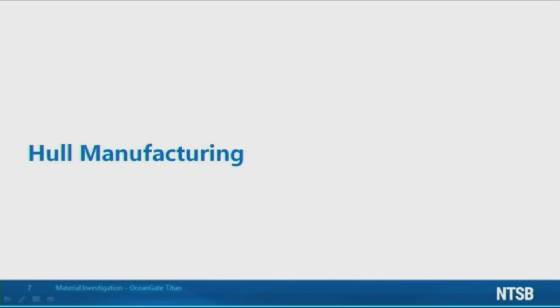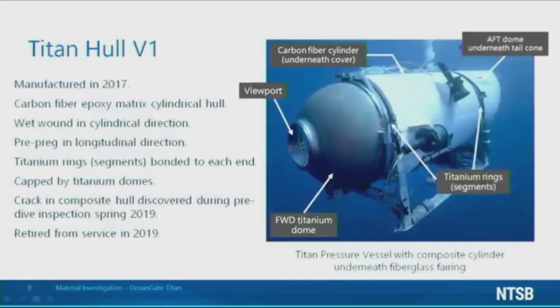I'll now discuss the manufacturing of Titan's composite hull. The Titan V1 cylindrical composite hull was manufactured in 2017 and was at the core of the Titan pressure vessel. The hull was manufactured using a combination of wet wound fiber for the circumferential plies and prepreg for the longitudinal plies. The ends of the cylindrical hull were capped by titanium rings called segments that were glued to each end. The segments in turn were mated to cylindrical titanium domes that were bolted on at either end, and the forward dome contained the affordance for the viewport. As previously noted, a crack was discovered in the composite hull and it was retired from service in 2019.